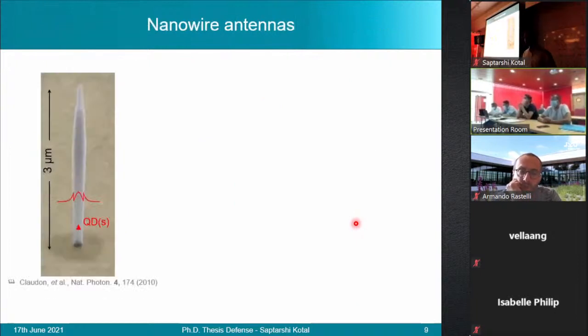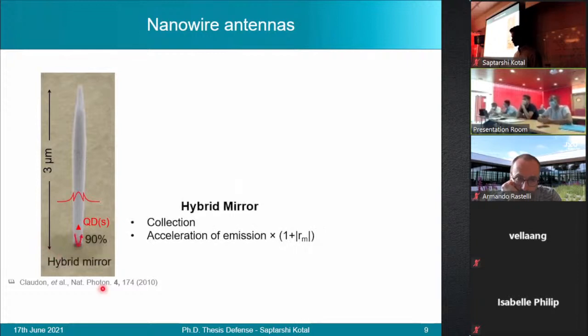Now, photons emitted by a quantum dot must be collected in some way to be able to use them. So what we do is we work on the two extremities of the nanowire that I've just shown you. First, we introduce a hybrid silica gold bottom mirror, which presents a reflectivity of around 90%. This helps to reflect the downward propagating emission. And in the process, it also results in a small acceleration of the spontaneous emission.